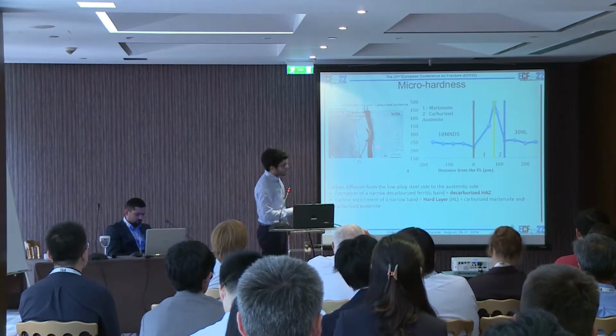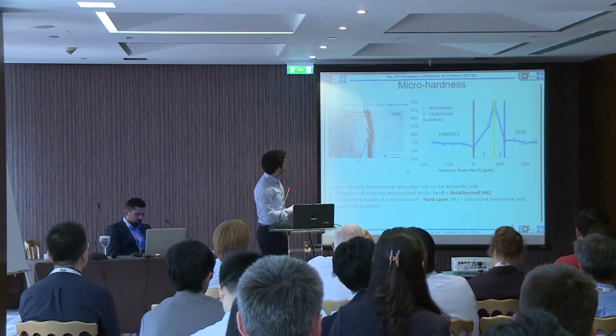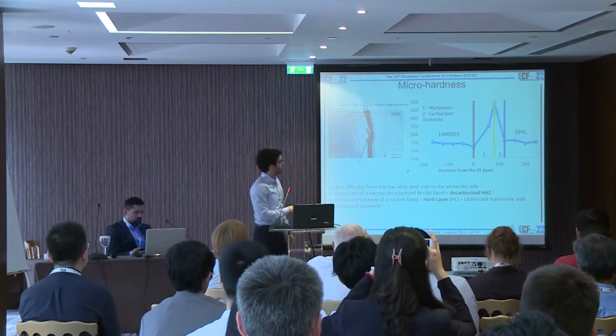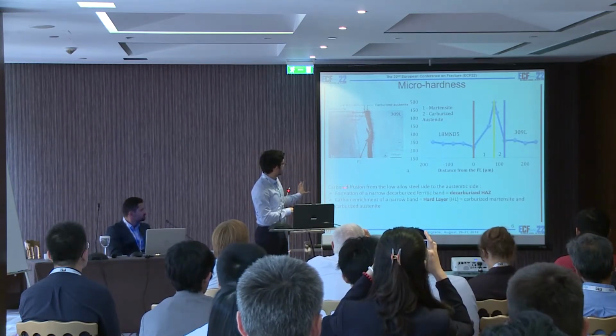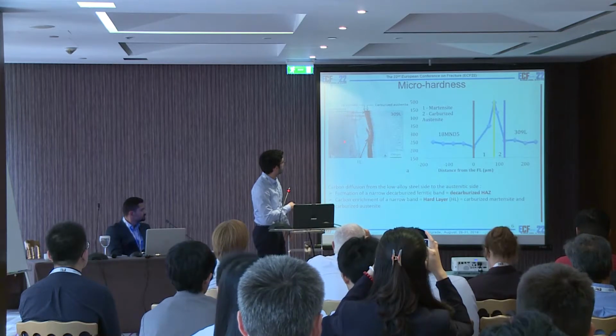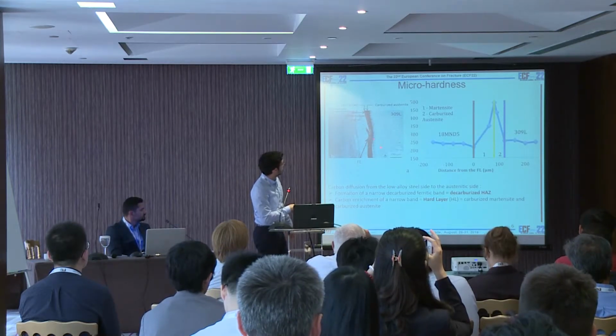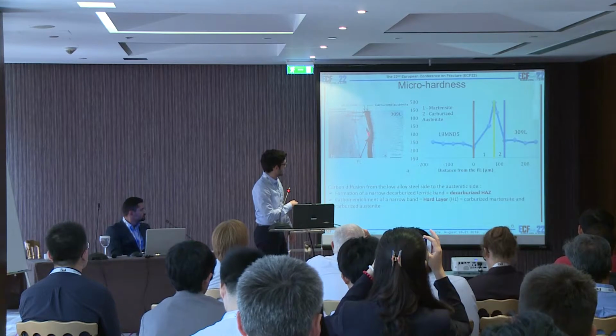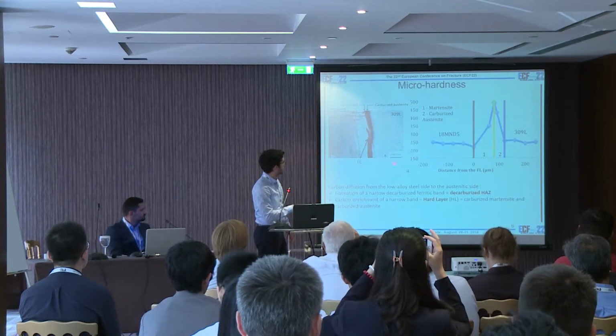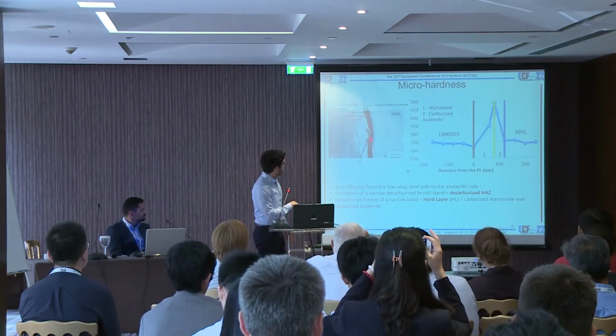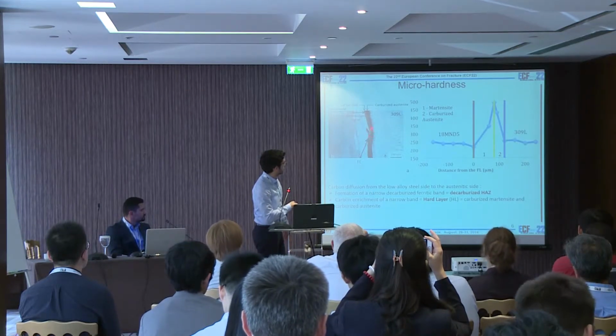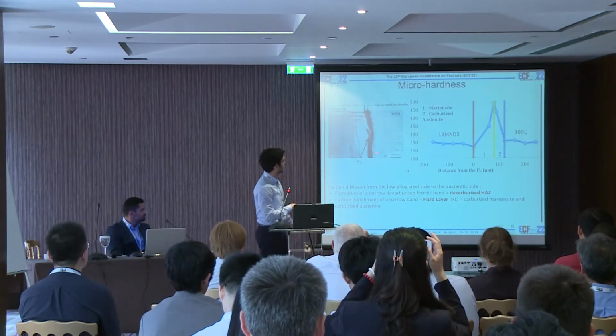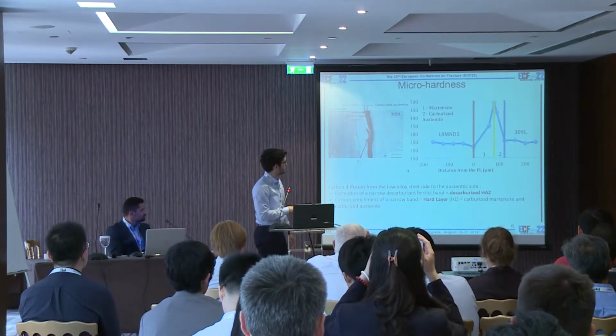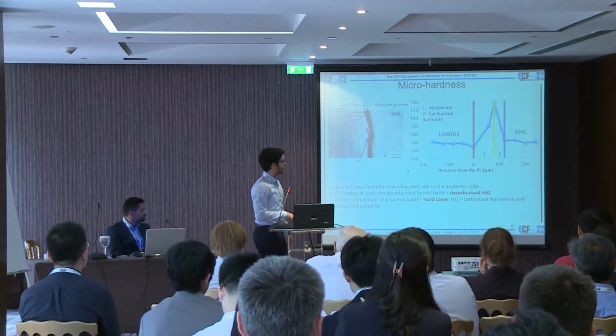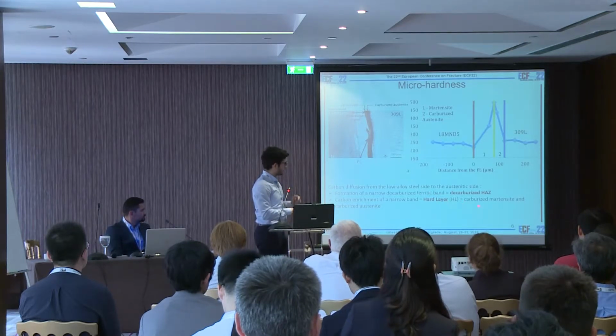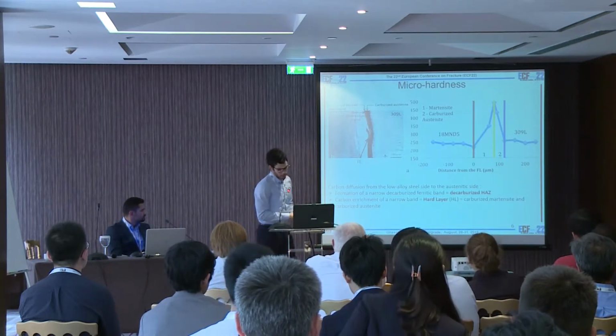So now let's analyze the carbide distribution across the interface, and we can see that there has been some carbon diffusion from the ferritic side to the austenitic side, creating a decarburized layer in the ferritic side, and causing carbon enrichment of a narrow band composed of the martensitic layer and the fully austenitic zone, which we will call the hard layer. So composed of carburized martensite and austenite.